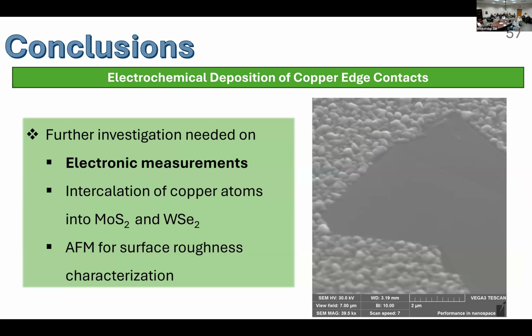And then for my electrochemical deposition of copper edge contacts, further investigation is needed on electronic measurements, comparing the contact resistance of the devices obtained here versus the contact resistance of our devices fabricated with our typical methods. We also have to look into whether or not this process intercalates copper atoms into our material. There has been some literature that says that copper is too large to intercalate itself into MoS2, but it has been used for doping in tungsten diselenide materials. So it might be interesting to change the material that we're using and see if we can also introduce doping apart from creating edge contacts.